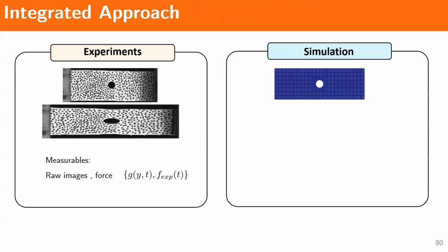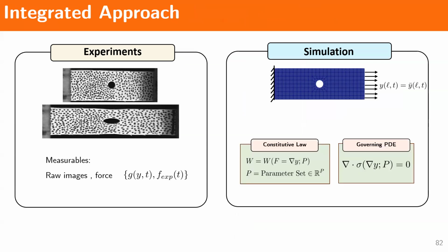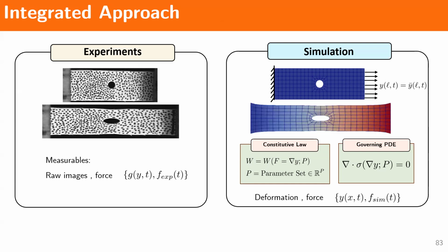Now you can emulate the experiments in our simulation. We can impose the exact same boundary conditions. You also know the physical phenomena that you're subjecting your material to. So you know your governing PDE here is just a typical equilibrium PDE. You also have to supplement our simulation with a constitutive law. So of course, this is what we are trying to get. We're trying to get our model. So this does not have to be the exact constitutive law. It just has to be parameterized with some parameters P here. Okay, so now we have all our information to do our simulation.